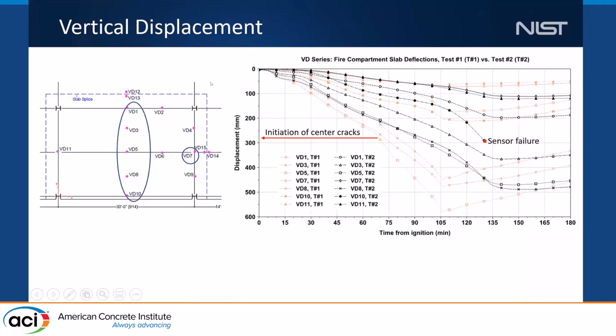Okay, let's take a look at some vertical displacement measurements between the first 2 tests. We put lots of string pots to measure the vertical deflection of the test floor slab. Again, the orange curves indicate the test number 1 results, and the black curves indicate the test number 2 results. As you can see here, the mid panel vertical displacement reached around 30 centimeters. We started to see the center crack developing on the south of this secondary beam. Once it happened, it changed the displacement gradient. The displacement rapidly increased afterwards.